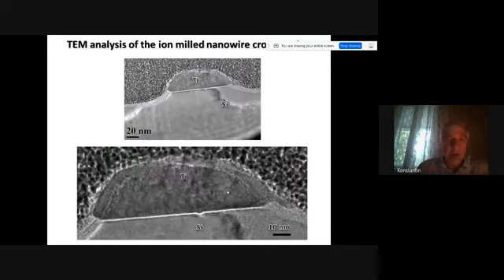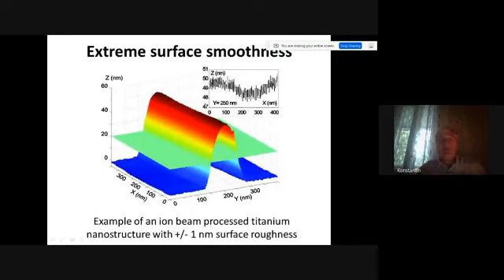And this is a transmission electron microscopy image of our nanostructure after etching. So here you see the silicon substrate, and this is the cross-section of the nanowire made of titanium. And a very important feature is that after several sessions of ion milling, we are capable of obtaining an extremely smooth surface. For example, this is the image of a titanium nanowire after several sessions of ion milling. We put then an AFM tip on top of it, and we scanned the roughness of the surface. And the inset shows that roughness varies with accuracy plus minus 1 nanometer. And this corresponds to roughness of plus minus 2 atomic layers.